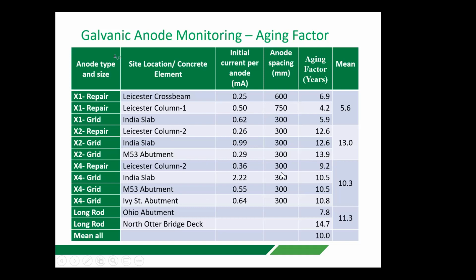And so on. These are more examples of the aging factor. We can see overall we achieved about 10 years, although on occasions we had 14 or so. So we now know which scenarios would give us the best aging factors, i.e. the longest period before the current reduces by half.